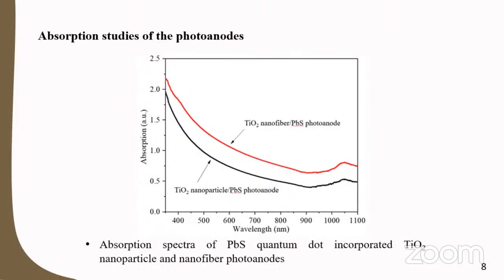Absorption studies of the photoanodes. This figure shows the absorption spectra of the PbS quantum dot incorporated TiO2 nanoparticle and nanofiber electrodes. The nanofiber photoanode shows increased absorption, which is due to the increased scattering in the electrode, and more light can be absorbed due to this.